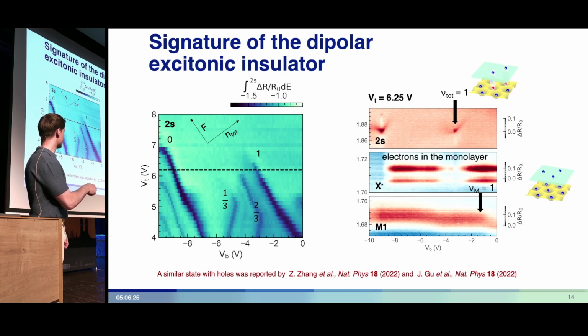So this overall incompressible phase somehow involves sucking the free charges out of the monolayer. What's happening is that exactly at this point, you have charge balance between the holes injected in the insulator and the number of electrons which have been injected into the monolayer.